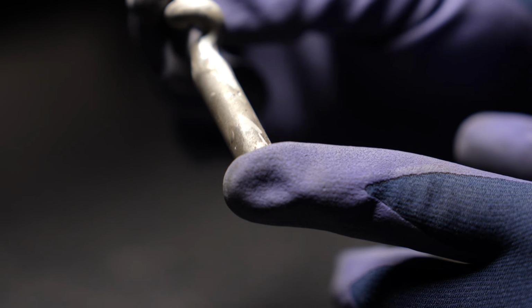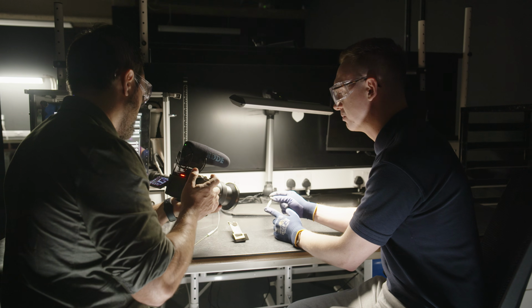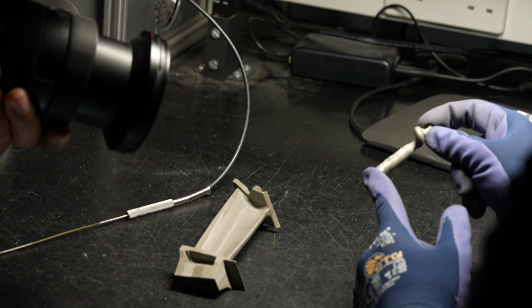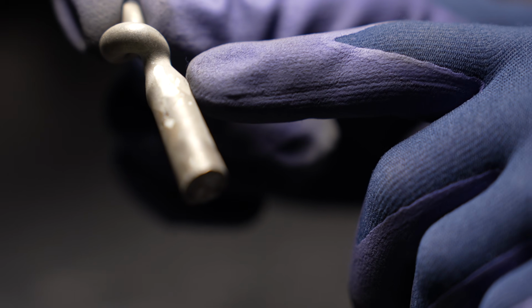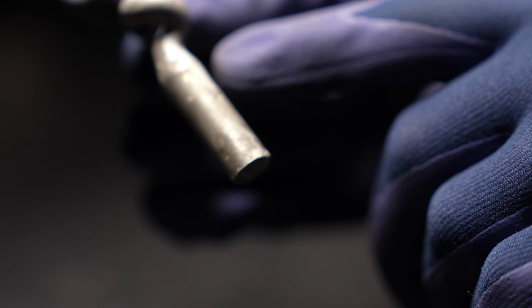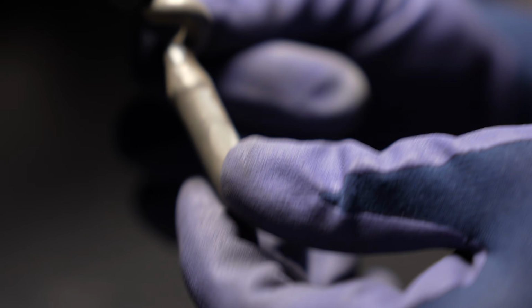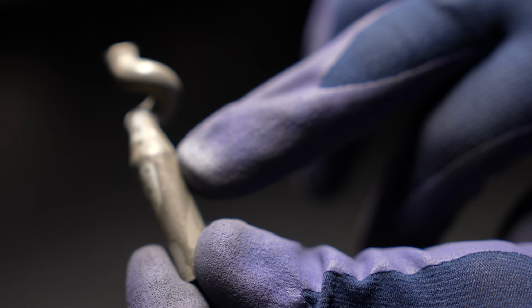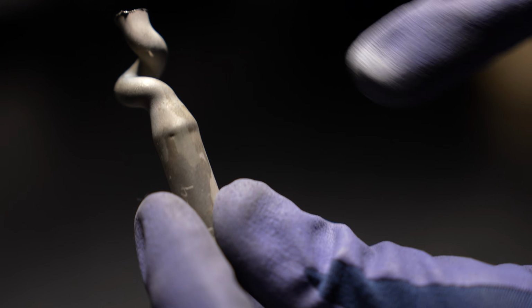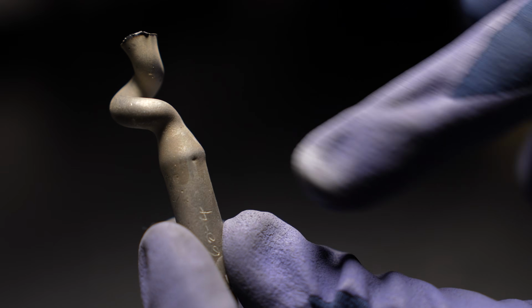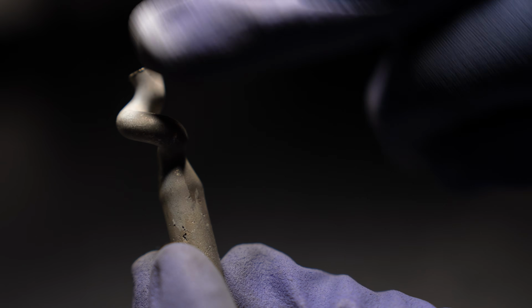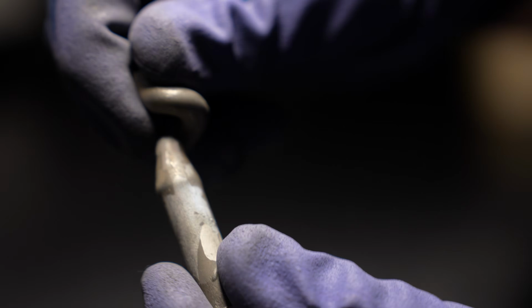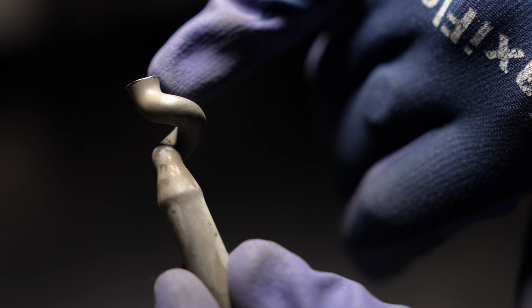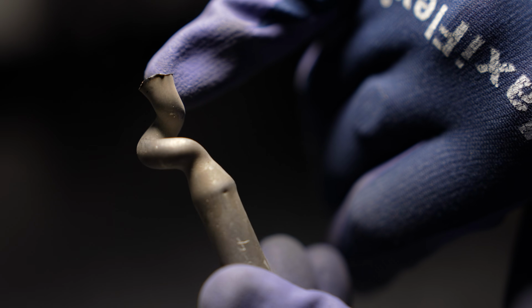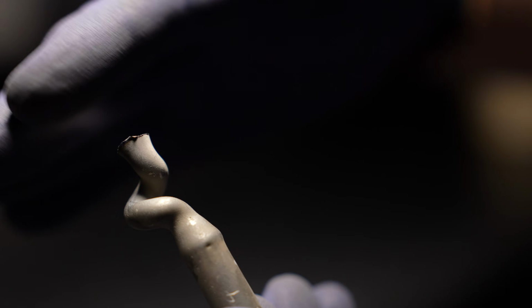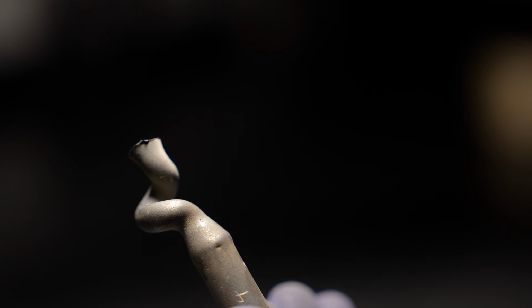That's crazy. So this is a starter attached to a spiral that we've etched so that we can reveal that structure. So you can see down at the bottom, we are starting to grow directionally solidified grains. And then as we're going up the spiral, the grains are starting to be choked out by the upper surfaces of that spiral until when we get to the top, we're just left with a single crystal. And then that allows that to grow right the way through the blade.